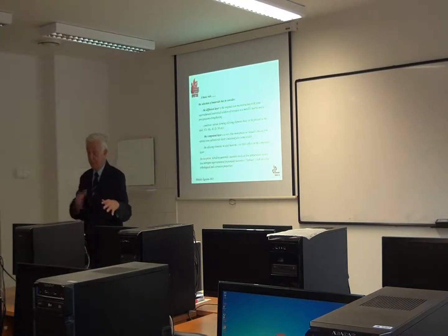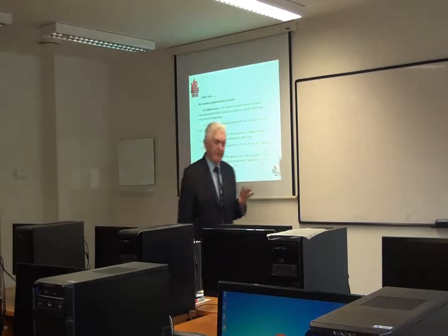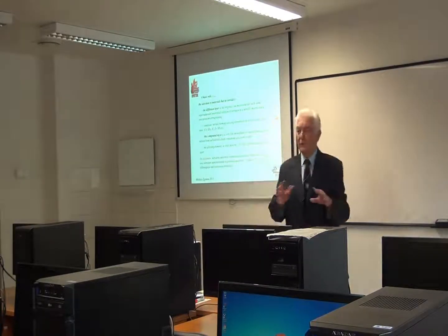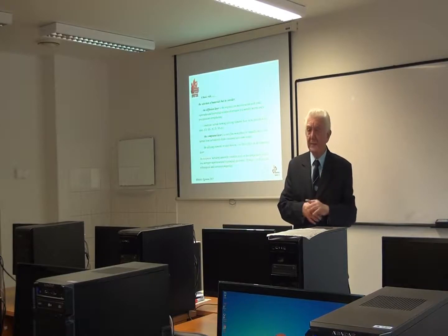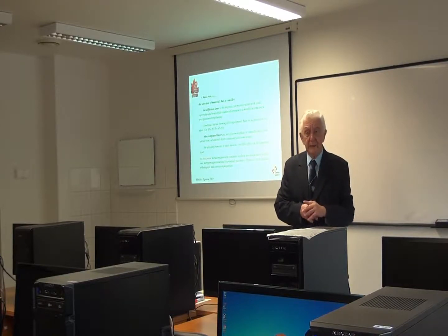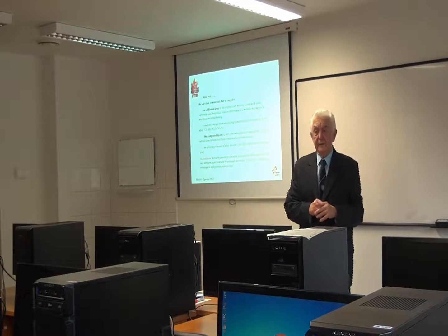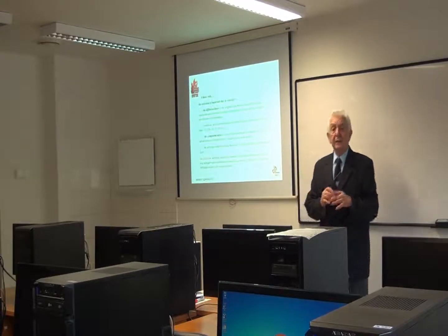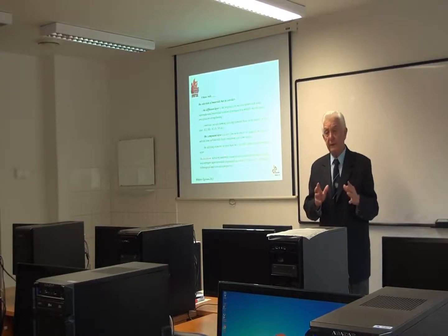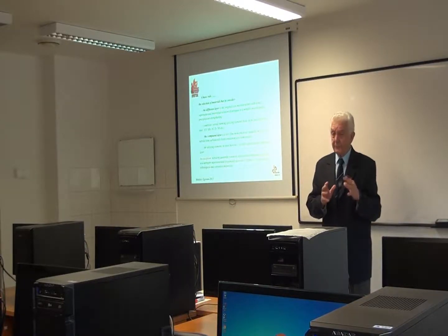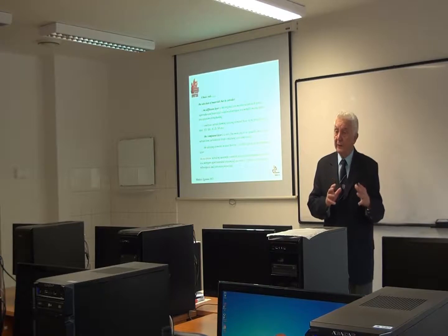Then the next one, which is, I said there's a dual character of the layer, is the compound layer. This compound layer is a very fine monophase, but in most cases it is dual phase or more complex nitrides and carbonitrides, which are in a very specific form. These nitrides and carbonitrides have a ceramic character.